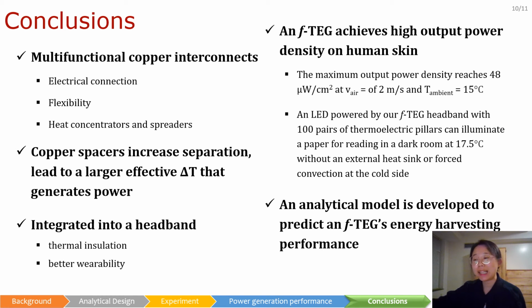Finally, please let me highlight the key messages again that we want to share with you. In this work, we adopt the multifunctional copper interconnects that serve as electrodes, flexibility enabler, and heat concentrators and spreaders. The copper spacer design increases the separation between the hot side and cold side of the device, leading to a larger effective temperature difference that actually generates power. The device can be readily integrated into a headband. We use fabrics to provide thermal insulation around the thermoelectric pillars and comfort for wearing.